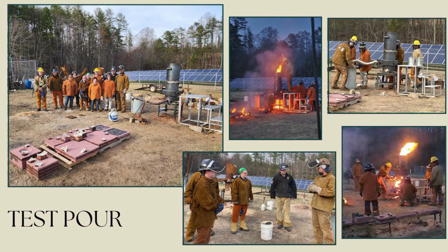Burn-in is whenever we start to light the furnace to ignite the metallurgical coke that's inside to heat it up to that 2800 degrees. It usually takes about an hour, hour and a half. Ours took maybe 4 hours, and that's not usually typical. The torch that we're using, the pressure wasn't able to get high enough to get that heat introduced quickly.